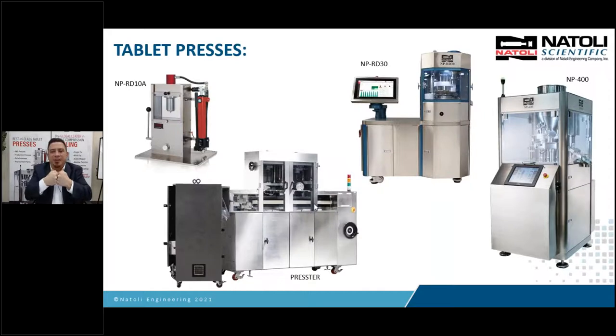We need to know that information so we're not overcompressing. And even on bilayer tablets, multi-layer, layer one compression has got to be below a certain level so you don't overcompress. And then when you compress both layers, they delaminate. So using the Heckel plots, we can determine what is the appropriate pressure or force for layer one compression. But even on monolayer tablets, this is very valuable. If we can characterize the API with the Presster, then we know what type of excipients to add in. Do we want plastic deforming excipients? Want brittle material? What percentages? So it's a very useful machine that allows us to understand the deformation properties.